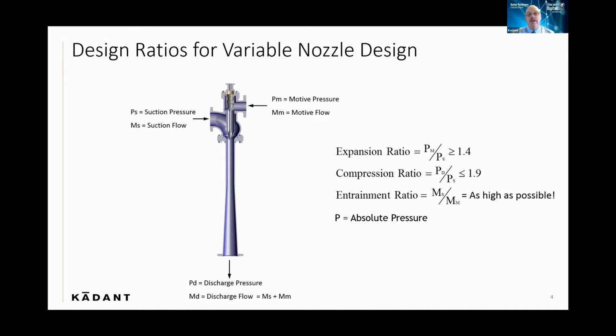And going on, once we know the design conditions or the operating conditions, there are certain ratios that we must respect. And these ratios do include some factor of safety. So if you go with these, you'll be on the safe side. The expansion ratio is the ratio between the motive pressure and the suction pressure. And we like that to be at least 1.4, and that's in absolute terms. The compression ratio is the discharge pressure over the suction pressure. And we like that to be less than 1.9.